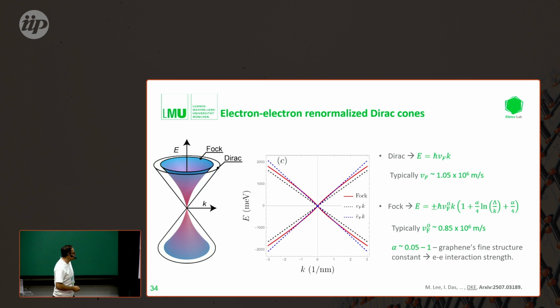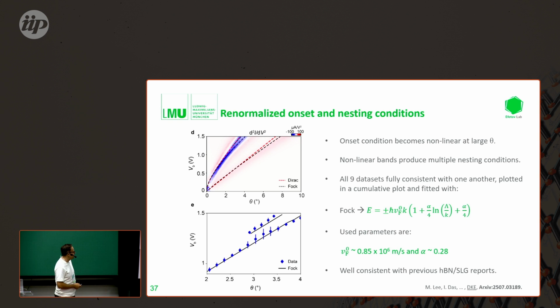So I have to say, we used the QTM to study some physics which was already known, but for me it was quite interesting to see how sensitive this QTM technique is. It can resolve tiny deviations of the Fermi velocity in the band structure, even at room temperature, and I think it's a very sensitive technique to study small corrections to the band dispersion.